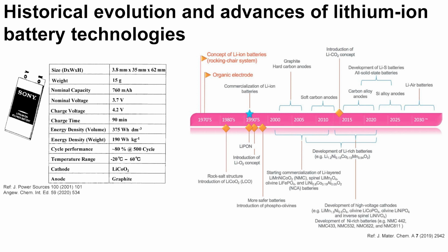Later, Goodenough and colleagues had adopted oxide cathodes based on the understanding. In 1979–1980, Goodenough et al. demonstrated that a lithium cobalt oxide, LiCoO2, can reversibly release and absorb Li-ions at potentials larger than 4.0 V, compared to Li+/Li, and enabled a 4.0 V rechargeable battery as coupled with the anode of lithium